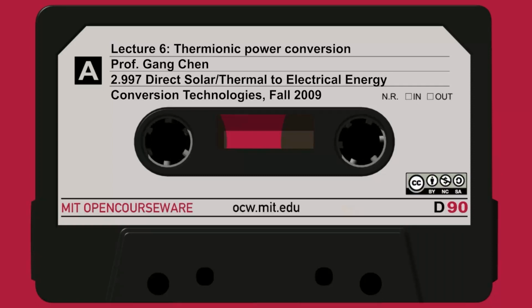This is how people make ohmic contact: you dope the region very heavily. And of course, you want to use the right metal to start with, so that the work function difference, the delta here, is not large. So if you want to make a contact, you want to know your work function, and you want to know the electron affinity of the material.